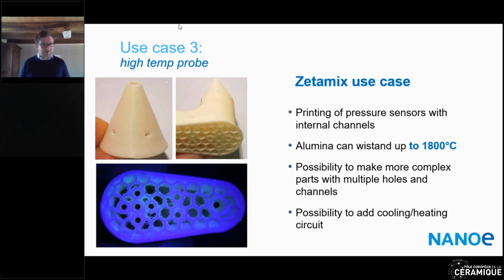Here are some actual pictures of parts printed by Avignon. I think some people from Avignon are here, so I can thank them directly for the courtesy of giving us those pictures. You can see some kind of pressure sensor probe with a few specificities. The first thing is it was made with obviously some internal channels. It was made in a hollowed out structure, which is better for thermal shock. It was made in alumina, which can withstand very high temperature. And we could even add some more complex parts with some more holes, potentially some cooling, heating circuits. Anything is possible. And on the bottom, you can see that it was inspected by dye checking, because obviously this part needs to be perfectly dense with no defects and no cracks.